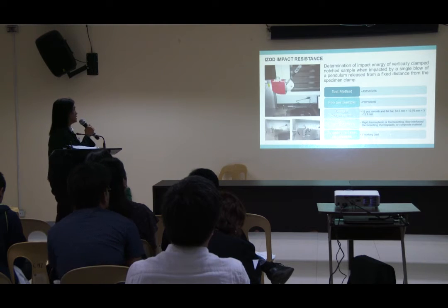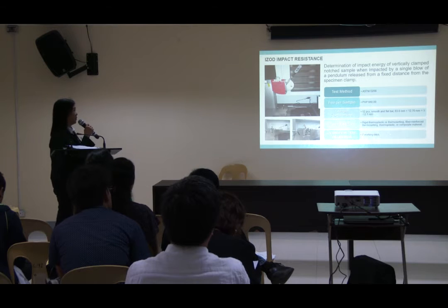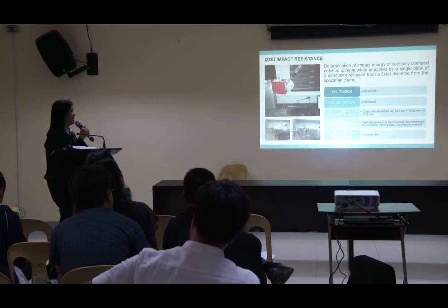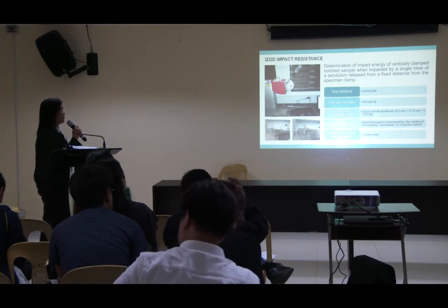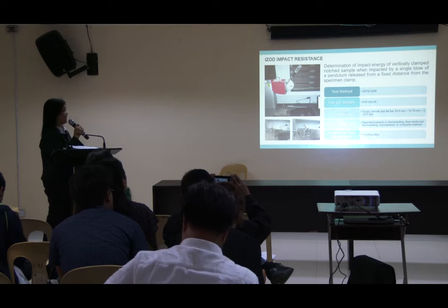For the IZOD impact resistance, it is a determination of the impact resistance of a vertically clamped, notched specimen when impacted by a single blow of the pendulum load released from a fixed distance from the specimen clamp. We use ASTM D256 for the test method.